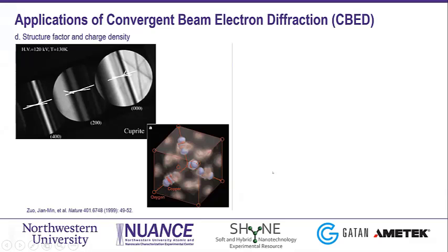Other more advanced application for CBED is structure factor, and from that you can determine the charge density map. So this is a nice example too, one very famous from back in the late 90s, where Jian-Min Zuo together with John Spence determined this charge density map of a cuprite sample by refining the structure factors using the CBED here.